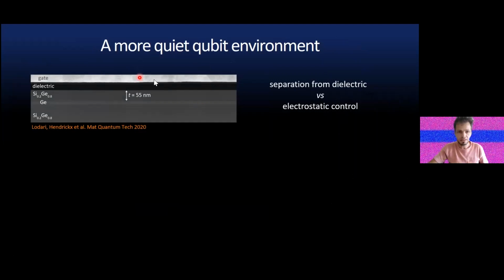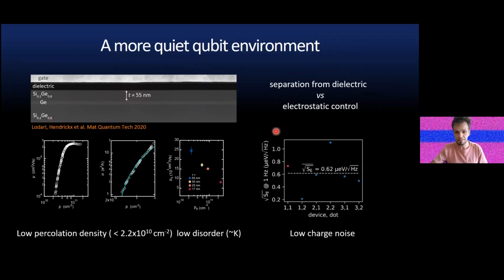The previous quantum wells were positioned at around 20 nanometers from the surface. Eventually, we moved the interface deeper. You cannot move it as deep as you want, because then you will lose electrostatic control of your quantum dots, so there is a trade-off you need to meet. We think we are at a good stage with these quantum wells, which are around 55 nanometers deep. Here we really saw a big advancement in the material, especially in the low density regime, which is the most relevant for quantum dot and qubit operation in the single hole regime, for example.